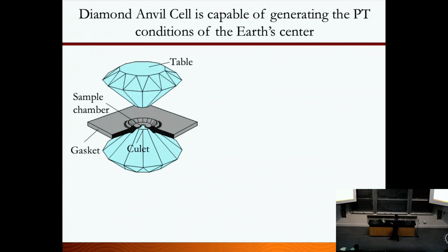So how do you get to these high pressures? Here's a simple cartoon. This is called the diamond anvil cell, the apparatus. You have two diamonds sitting opposite to each other. In between those two diamonds, we put a metal gasket, a pre-indented gasket, so that it takes the shape of the diamond, and you can make a sample chamber right here. By applying force from top and bottom, you can generate the pressure.